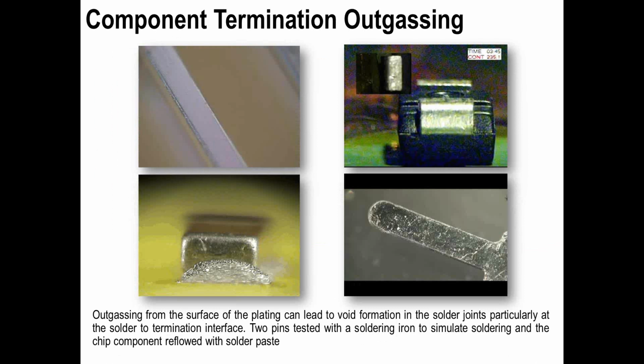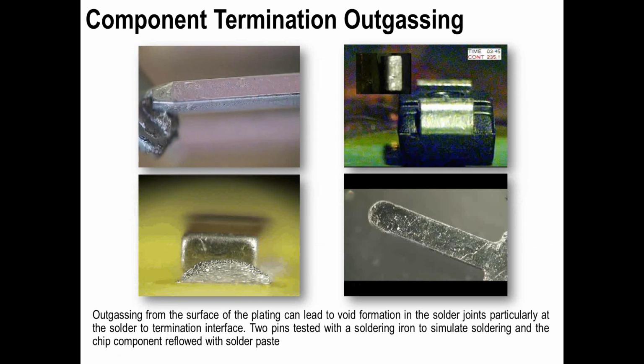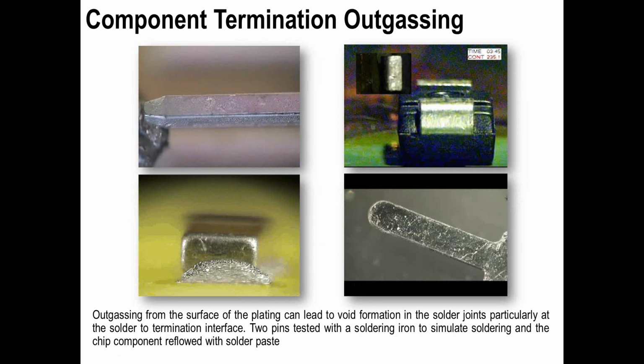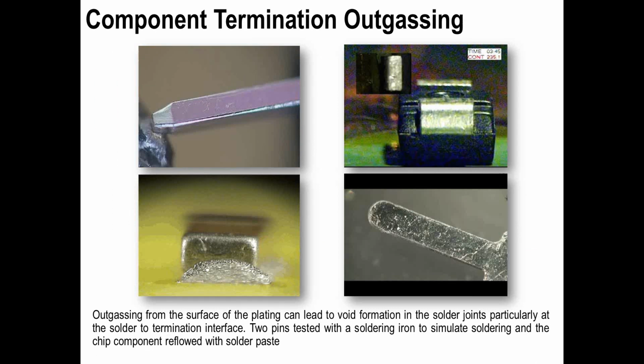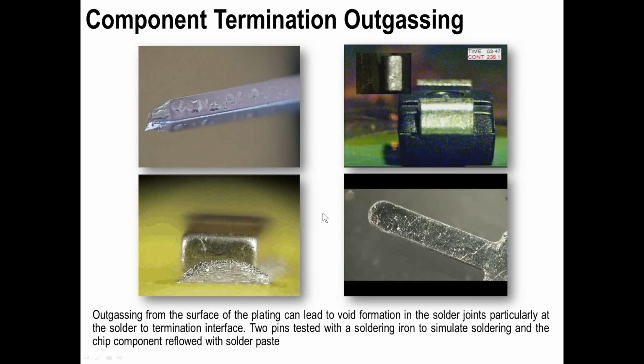First of all, what we're showing here is a pin with tin plate on, and we're basically reflowing the tin plating. And even online with this sort of sluggish video, you should be able to see the gassing from the surface. You can actually see bubbling on the surface of this particular pin and some de-wetting. On the second video, on the top right, again what we're doing is a video simulation, and what you can actually see is gassing from the plating on the surface of the component.